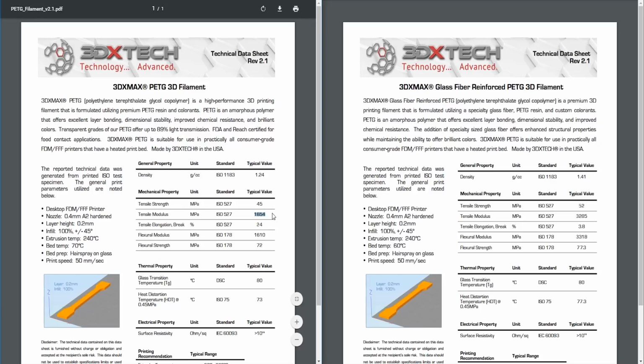Twice. So you're doubling the stiffness of the PETG. You're dropping the elongation by 6 times, but also doubling the flexural modulus, but just barely increasing the strength. So you're just increasing the stiffness, because you can't really increase the strength, because the matrix is your resin, which is the PETG, and your reinforcement is the glass fiber. So the glass fiber is just going to add reinforcement inside your matrix, but your matrix is still going to fail at the same strength as it is originally. Plus, it might move it a little bit up, which it did here. So just barely moved it up.